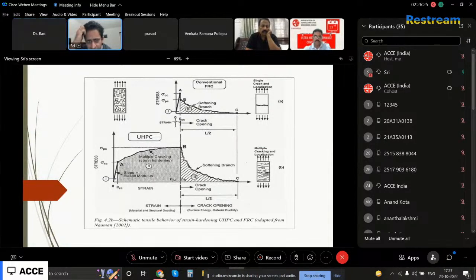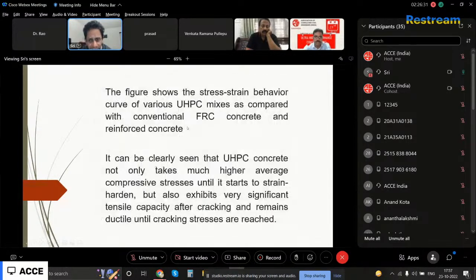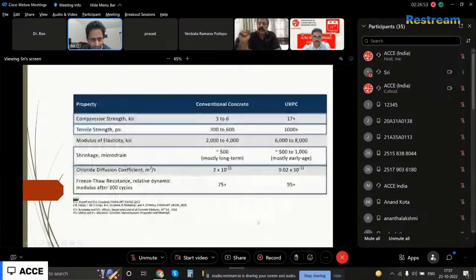Then this is another slide talking much more about understanding the behavior again. You see the material ductility, all that. I'm not spending much time, guys. Sorry. The important conclusion is that we clearly see UHPC not only takes much higher average compression until it starts to strain harden, but also exhibits very significant tensile capacity after cracking and remains ductile until cracking stresses are reached.